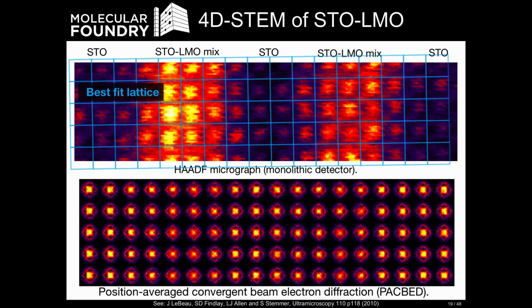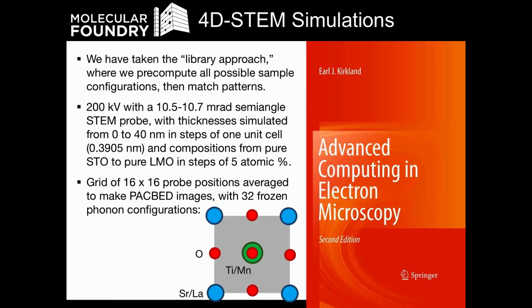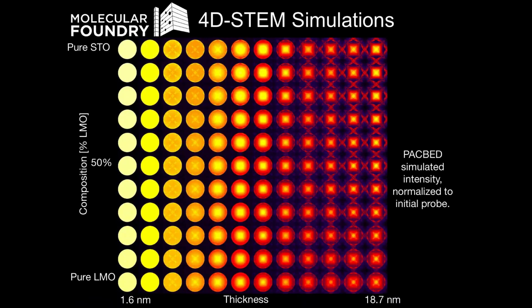It's quite subtle in this particular data set. But as you travel across from the STO layer to the STO LMO layers, you can see clearly the scattering cross section is changing a little bit. If we combine that with multi-slice simulations, and I'm not going to go into the details here, we're using the cross sections, scattering potentials, etc., from Kirkland's book, we can make a library of all of our scattering CBED patterns as a function of composition and thickness.